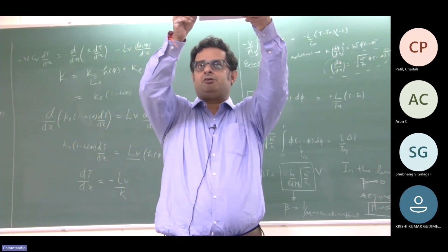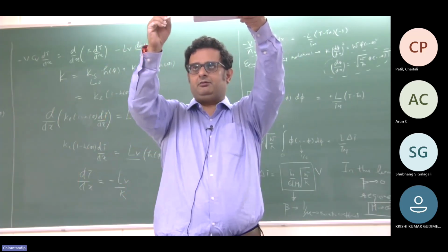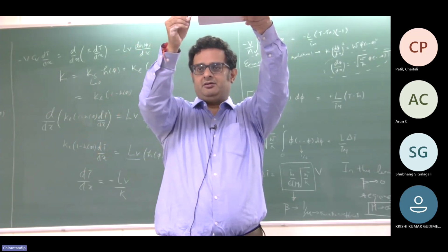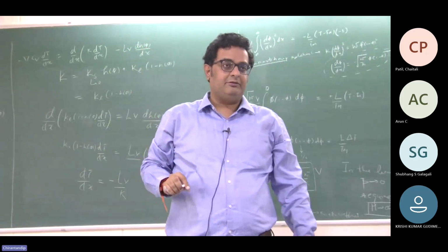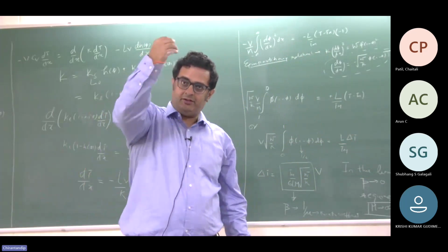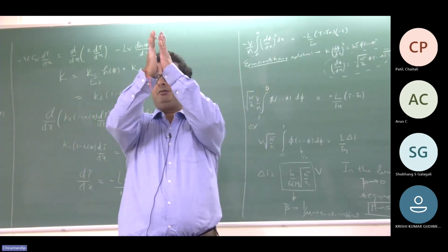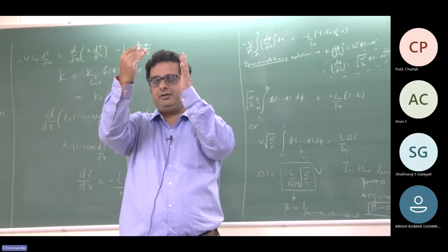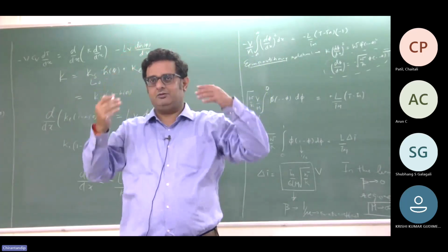So necessarily, when you do the extrapolation of the temperature from the interface, from the solid side, and the temperature from the liquid side, you are going to have a different thing. This guy is going and joining here. So the effective composite temperature at the interface will have it. So essentially what it means is you look at the solution from the solid side and look at the solution from the liquid side far away. That means if I think of removing the interface, but how do I remove the interface visually? I extrapolate what I see on the macroscopic bulk liquid and macroscopic bulk solid, and whatever they mean is essentially my solution.